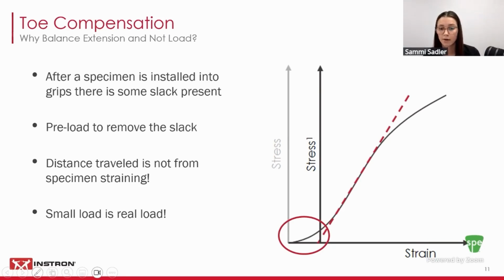In order to obtain correct values such as modulus, strain, and offset yield point, this artifact must be compensated to give the correct 0 point on the strain or extension axis. So in short, this will produce incorrect modulus data and strain data. So it's important to remove the slack before starting the test. After the material is placed into the grips and the grip attaches onto the specimen, there will be some compressional forces that are exerted on the material, and that also must be removed.